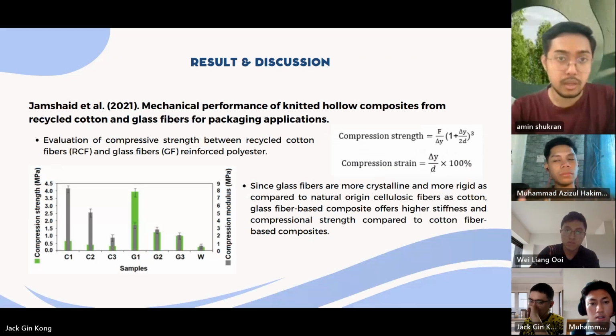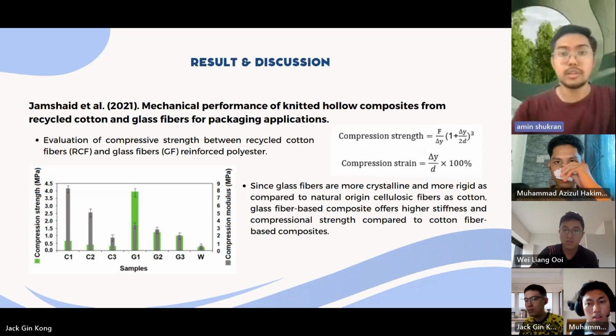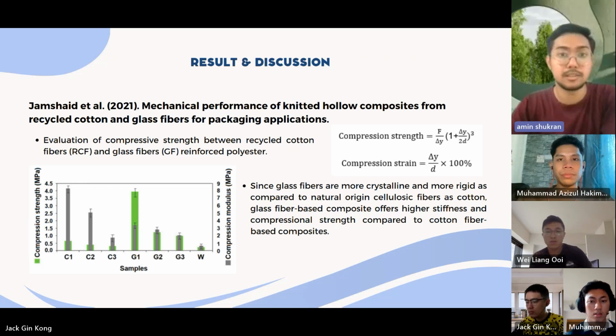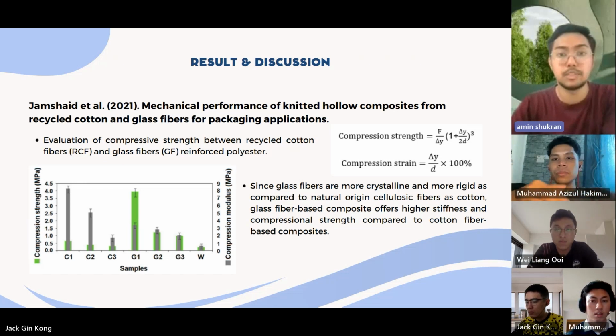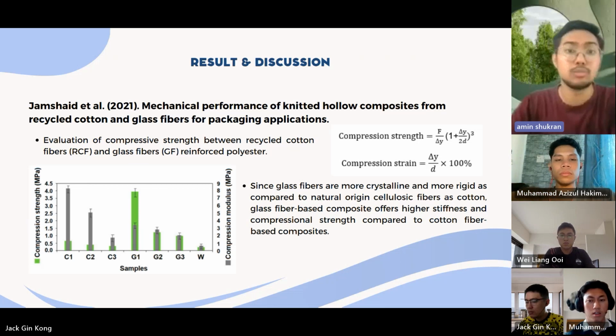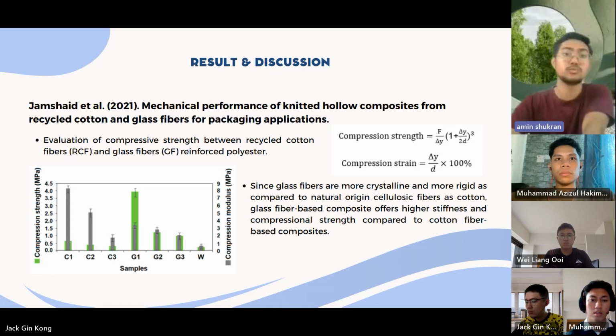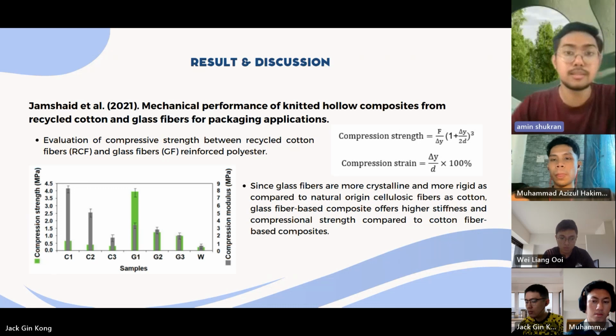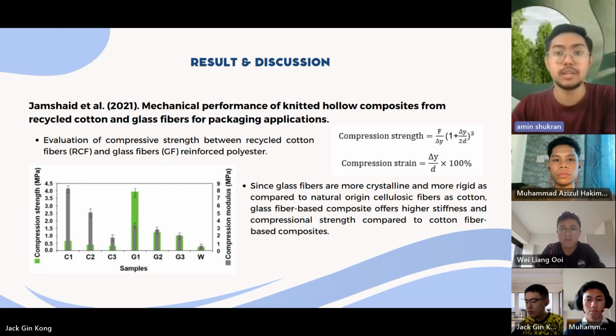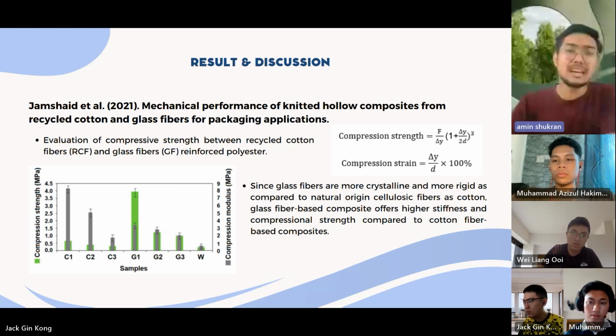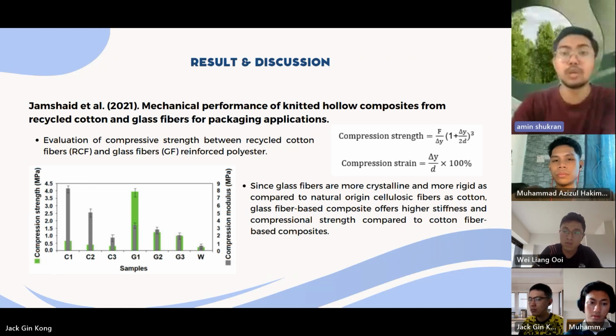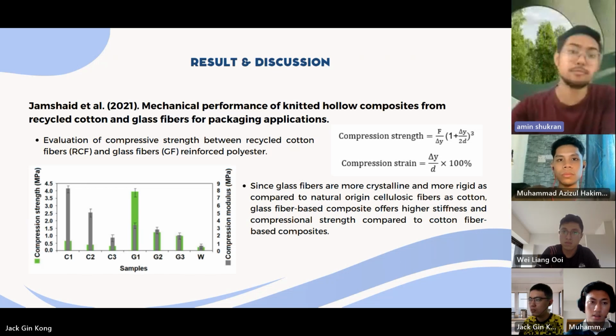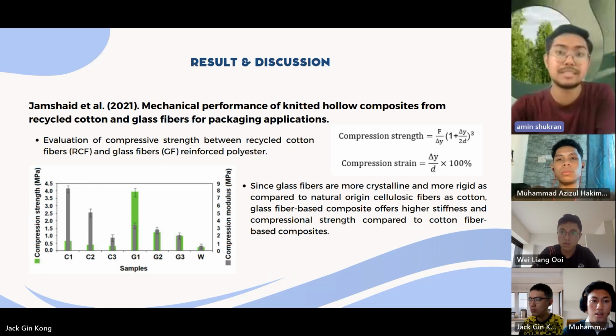Next, another finding worth discussing is the evaluation of compressive strength between recycled cotton fibers, RCF, and glass fibers, GF, reinforced polyester. It is valid to relate to the study on tensile strength because both are normal forces per area, differing only by pulling and pushing forces. The total samples tested are 7 samples: 3 RCF, 3 glass fiber, and 1 control experiment sample of double layered cardboard. Since glass fibers are more crystalline and more rigid as compared to natural origin cellulosic fibers such as cotton, glass fiber-based composite offers higher stiffness and compressional strength compared to cotton fiber-based composites.